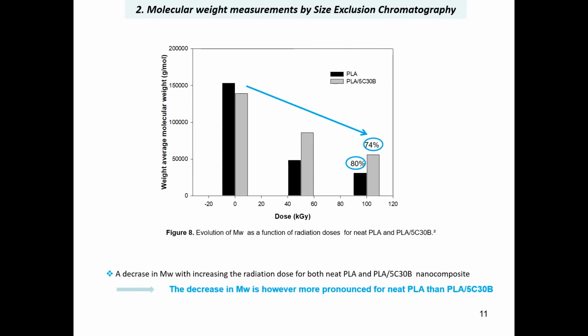And this is also measured by molecular weight changes. We know that a decrease in molecular weight, as shown in figure 8, in both samples, that is neat PLA and the PLA-based nanocomposite, with the radiation dose, expresses the occurrence of a chain scission mechanism. However, the decrease in molecular weight is observed to be more pronounced for neat PLA than the PLA-based nanocomposite, as indicated by a 74% decrease in molecular weight for the nanocomposite, whereas 80% for the neat PLA.